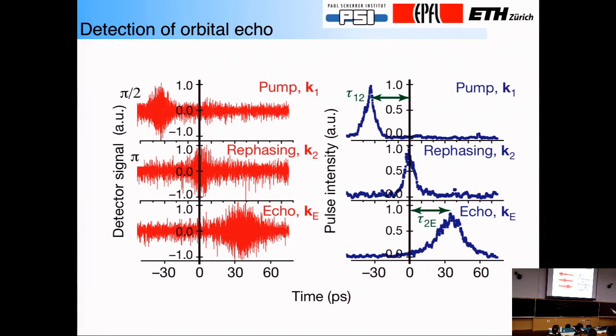And so I've got my pump, my rephasing, and then my echo, and you can see immediately, you can read off immediately that the time between the pump and the rephasing is precisely equal to the time between the echo and the rephasing pulse. I can rectify these pulses because these are actually interferograms, and of course interferograms have a phase and an amplitude at each point.